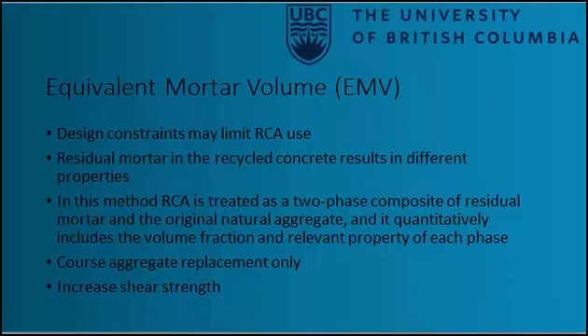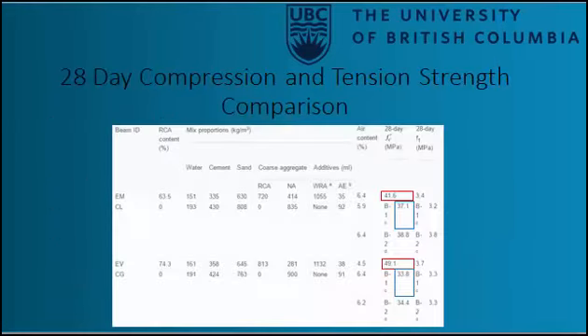This is the equivalent mortar volume method. In this method, recycled concrete aggregate is treated as a 2-phase composite of residual mortar and the original natural aggregate. It quantitatively includes the volume fraction and relative properties of each phase, which allows us to use the original standards. This table shows the results of their study. As you can see, the 28-day strength is similar to natural aggregates for both tensile and compressive strength. Now Brandon will talk about the uses of recycled concrete.